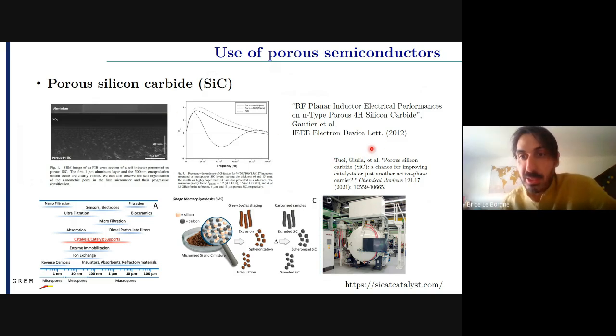Actually, there is a nice recent study that talks about the opportunities for silicon carbide or porous silicon carbide, especially in the field of catalysis. It's something that we developed with this team in Catania. And I think there is a lot of space, because as you can see, you can form porous silicon carbide as catalyst or as support, and in a quite wide range of pore size. So I think it's going to be something in the next years. You already had two presentations, I think, about this material in last PSST, but I think it's going to grow a bit. So it's very interesting.